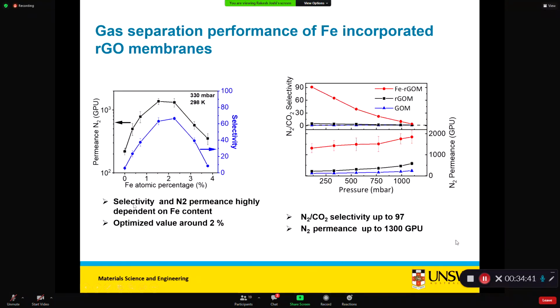You see here, when we go from Fe atomic percentage of 0 to high, it shows a very high selectivity of 97 at around 2%. The optimized value of Fe is 2%, and the permeance value is also very high. We wanted to do CH4 and CO2, but in the lab conditions, we couldn't find a CH4 source at that time. We published that paper in Advanced Materials. I think for any graphene oxide-based material, this is the benchmark.